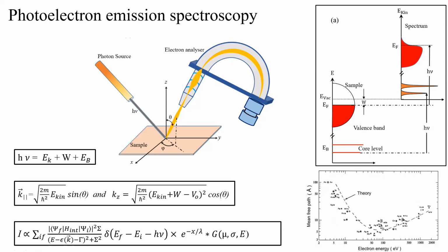Yeah, of course, it breaks. When you break these Cooper pairs, because of the binding energy of these Cooper pairs, you get intensity at that much energy. So you will basically see a sharp feature at the gap value delta. Say the gap value is 10 meV, you will see no intensity from the Fermi energy to 10 meV, but you will see an intense feature at 10 meV. So of course you break the Cooper pairs also. Okay, I guess that answers Joydeep's question. He says that it's fine.